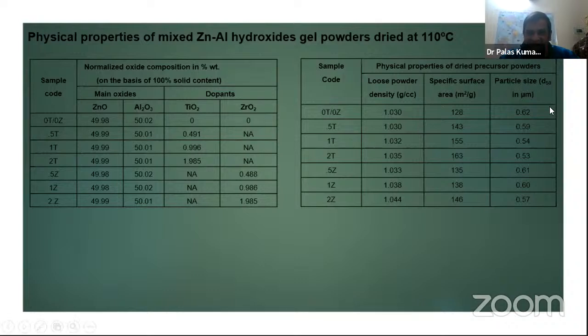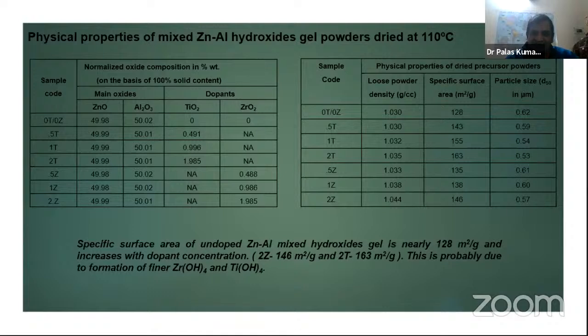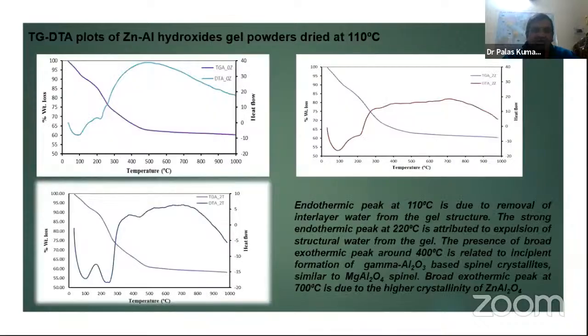their particle size by D50. And this is obvious, due to formation of titanium hydroxide and zirconium hydroxide, which are quite fine, which makes the surface area improved and higher, and of course reduces the average particle size.